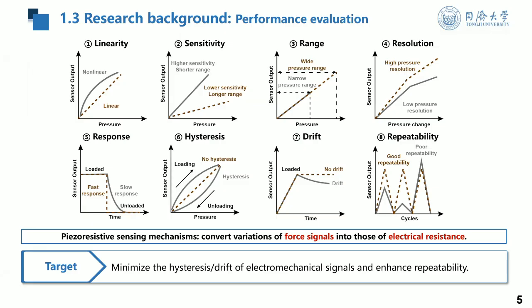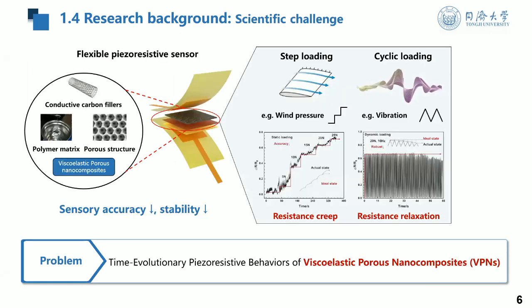So our target is to study the mechanism and then minimize the hysteresis and signal drift of the electromechanical signals and enhance the repeatability of flexible sensors based on nanocomposites. First, for nanocomposite based sensors, we use conductive carbon-based fillers to improve the conductivity. And we also consider the polymer matrix. And then we introduce different levels of porous structure to control the deformation and the stiffness of the sensor structure.